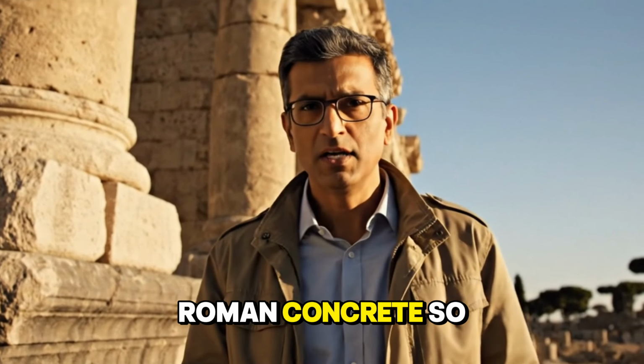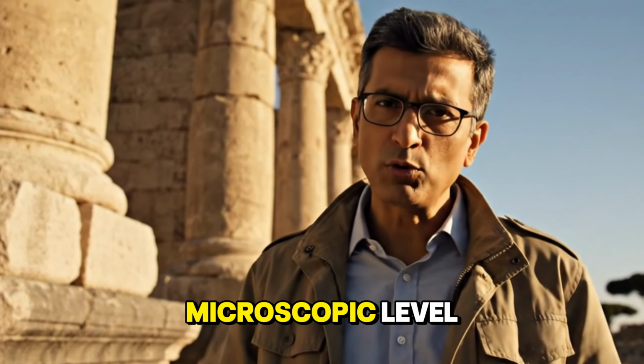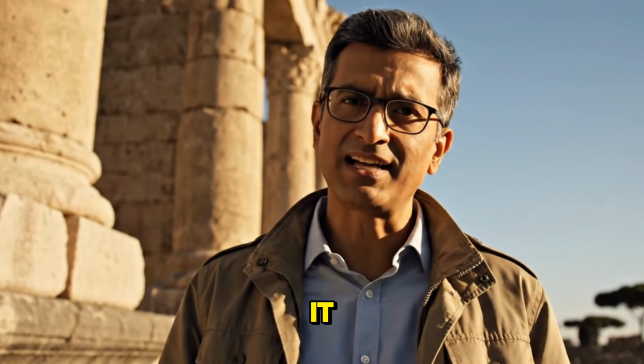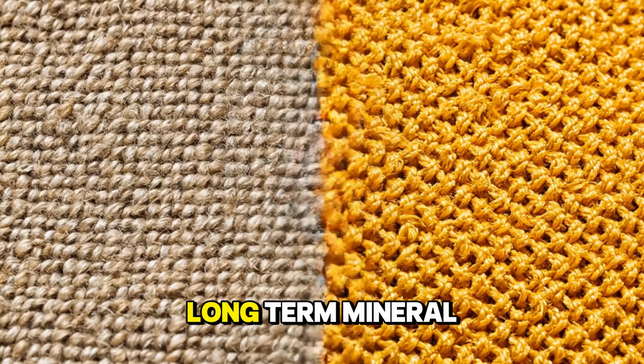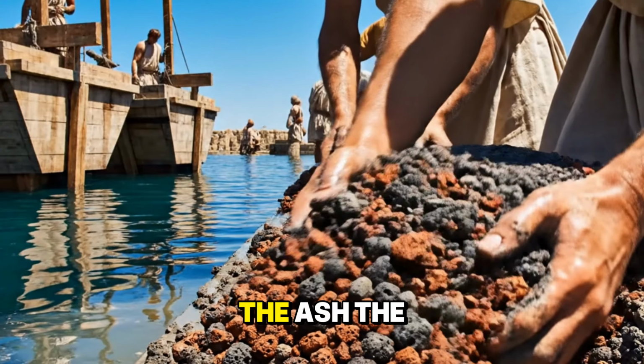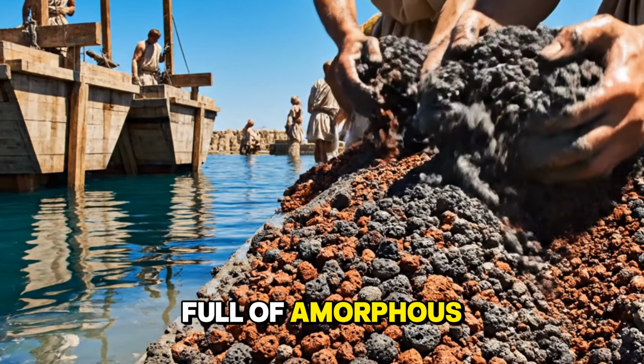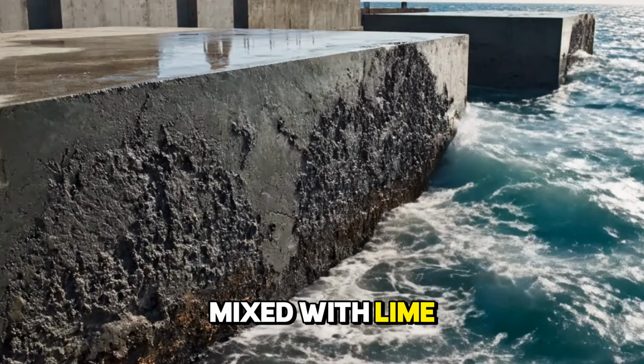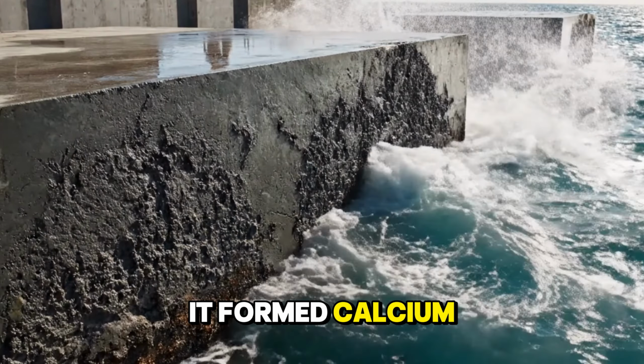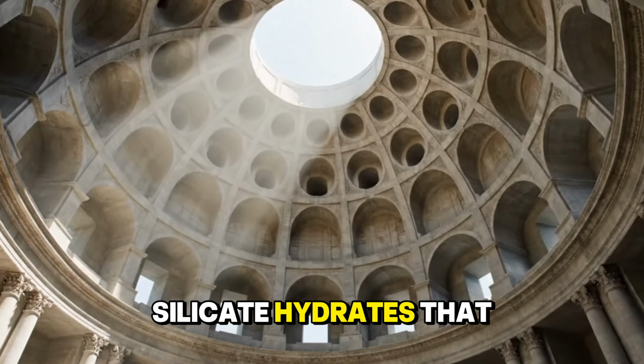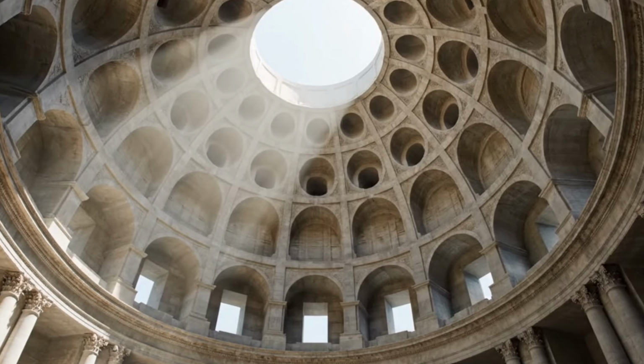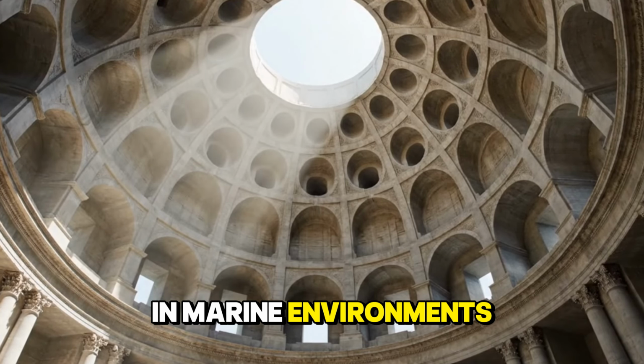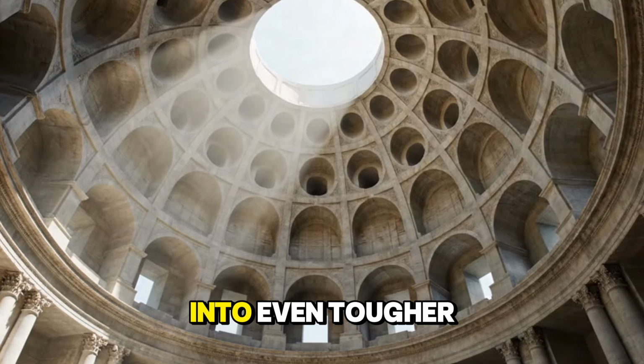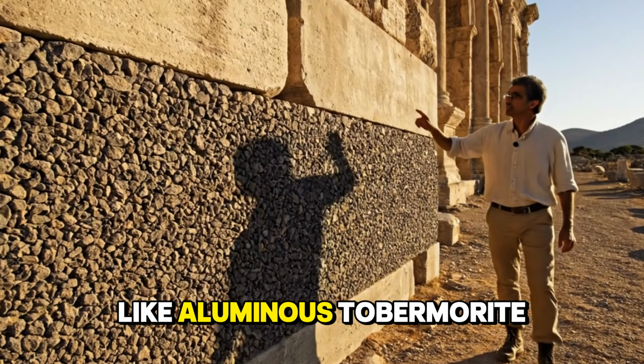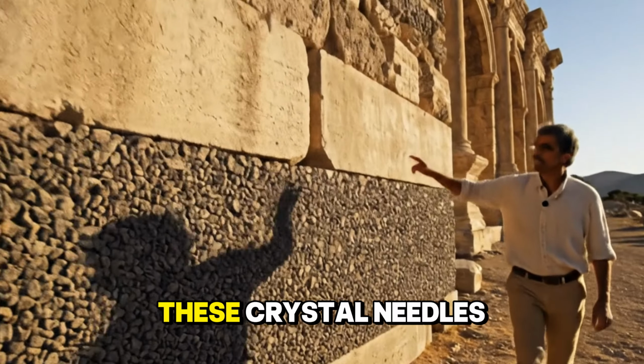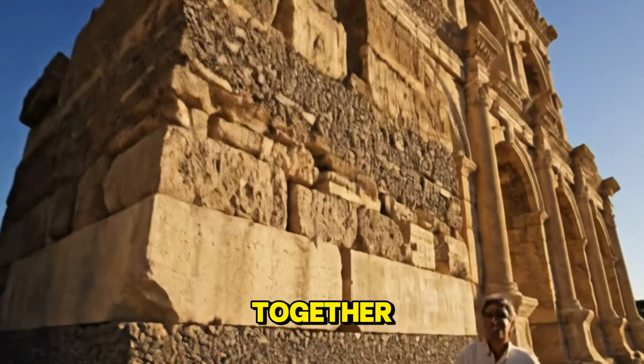So what made Roman concrete so sturdy at the microscopic level? Two phrases unlock it: pozzolanic reactions and long-term mineral evolution. The ash the Romans used was full of amorphous silica and alumina. Mixed with lime and water, it formed calcium-aluminum-silicate hydrates that are stable and dense. Over time, especially in marine environments, those hydrates morphed into even tougher minerals like aluminous tobermorite and phillipsite. These crystal needles stitch the matrix together.